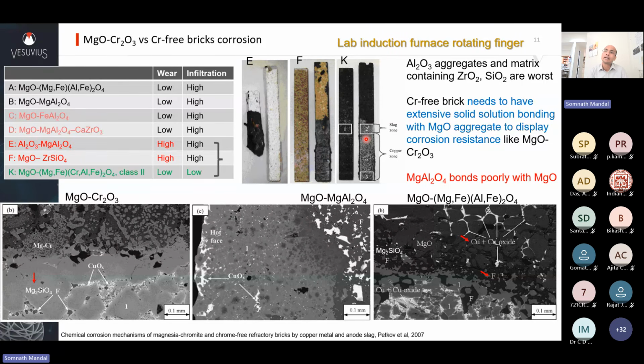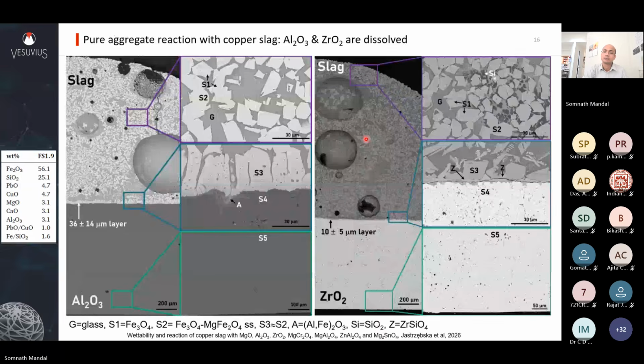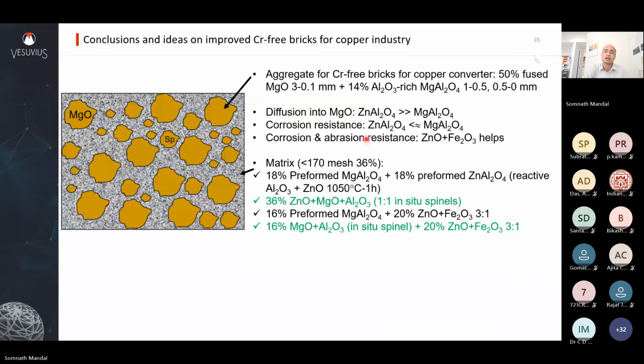Yeah, magnesia bricks. So magnesia zinc aluminate or magnesia spinel zinc aluminate. So basically magnesia aggregates. And let me show you a concept like this, where you have magnesia aggregates and some spinel aggregates, and you have a matrix of magnesium aluminate and zinc aluminate with some amount of fine magnesia. This is also a candidate refractory for RH degasser snorkels. So this is a 1600 degrees Celsius steel making application directly in competition with magnesia-chrome bricks. Some works have already been done. As far as I know, these have already been trialed. So these are for sure good candidates.